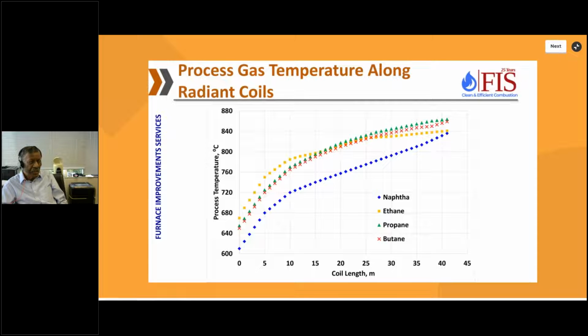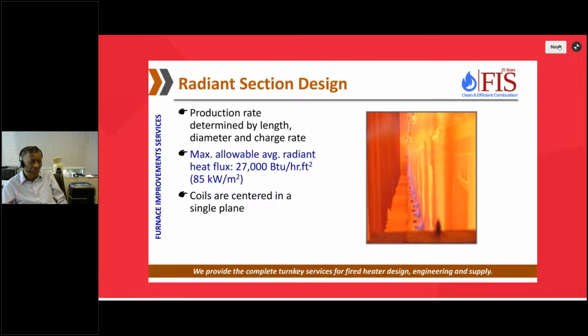This is a very nice graph drawn by our team, and it shows the coil lengths. Typical coil lengths are anywhere between 100 to 140 feet. That's typically the coil length. And it shows the coil temperatures, the fluid temperatures, process gas temperatures. This is for the naphtha, and the yellow is for ethane, which is another very common feedstock. And we are talking of going all the way up to 840 degrees centigrade, which is about 1500 plus 50 or even higher. As I said, maximum allowable flux is typically around 27,000 BTU per hour per square foot, or 85 kilowatts per square meter. Coils are in the center. That's typically how these things are designed.